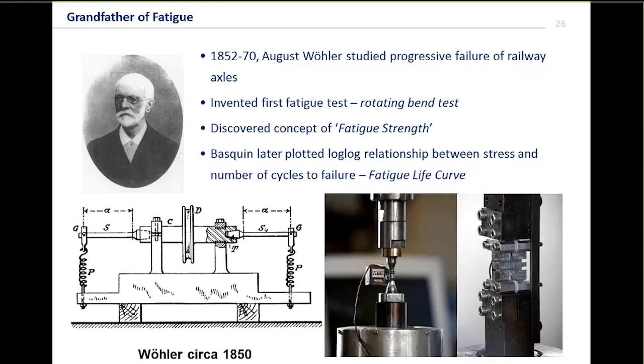As well as the Wöhler machine, we see these axial machines. The photograph on the left is showing a typical strain-controlled test on bar stock. This is an hourglass specimen with a clip gauge attached to it, and you'll see lots of those in our lab if you were downstairs at the moment. Next to it, you see a slightly strange arrangement. We're not testing that great big fixture.